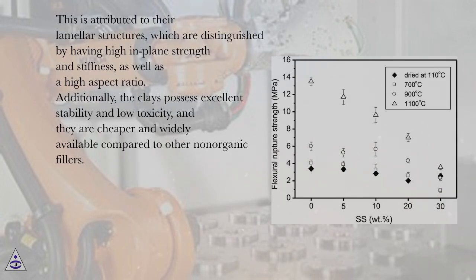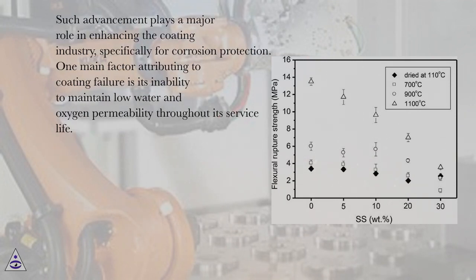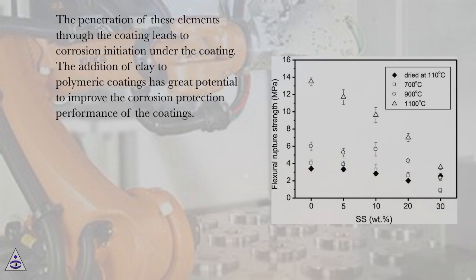Additionally, the clays possess excellent stability and low toxicity, and they are cheaper and widely available compared to other non-organic fillers. Such advancement plays a major role in enhancing the coating industry, specifically for corrosion protection. One main factor attributing to coating failure is its inability to maintain low water and oxygen permeability throughout its service life. The penetration of these elements through the coating leads to corrosion initiation under the coating. The addition of clay to polymeric coatings has great potential to improve the corrosion protection performance of the coatings.